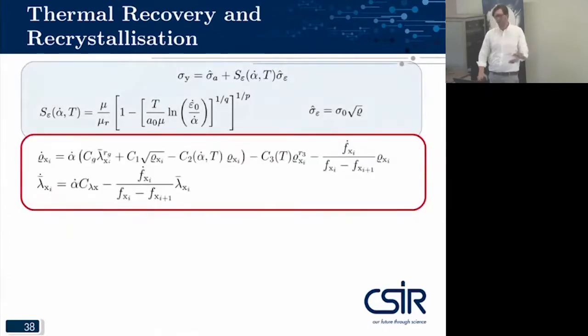Now, in the state variable, you can see where we originally had that Voce model that was quite simple. Here we've included a lot of different effects. So we've included misorientation in the grains as they deform. We've included multiple cycles of recrystallization where some of the material gets eradicated based on the creation of new grains within the material. So it's a slightly more complex evolution equation.